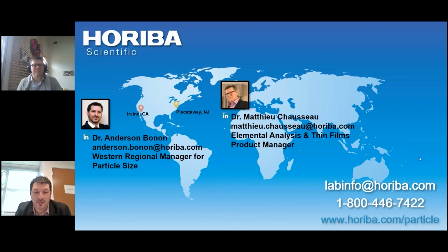Okay, yes, they're actually very complementary. To detect oversized particles, dynamic image analysis is a little bit more precise than laser diffraction. But when you're going for the small particles, it's a little bit the reverse, because you can get a much better dispersion for the metal powders in laser diffraction than you do for image. So if you want to quantify very precisely the threshold of your larger particles, then dynamic analysis would be a little bit better.